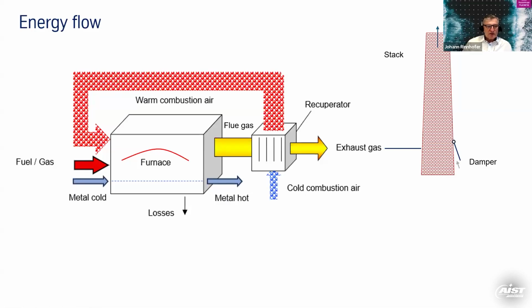There are also other options like recuperative burners. So you have the recuperator in the burner system. They are usually used for normalizing furnaces and also some sort of lower temperature furnace, a bit less than 1000 degrees approximately. And we also have the option to go to regenerative burners, which are dealing with very high temperatures. You can use them in the hot zones of a furnace. They have preheating temperatures of around 1000 degrees Celsius and even more. But you can use them only in the hot zone of the furnaces, obviously.